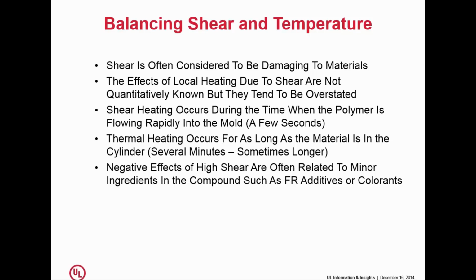If, on the other hand, you choose to add the heat by turning up the temperature of the barrel, that heat is applied for as long as it takes for the material to make its way through the entire injection cylinder. And that, at minimum, is going to be 3, 4, 5 minutes. In many cases, it's a lot more. I've seen residence times in excess of half an hour. So you ask yourself, would you rather expose the material to high heat for a few seconds or for 30 minutes? And I think the answer is pretty obvious.